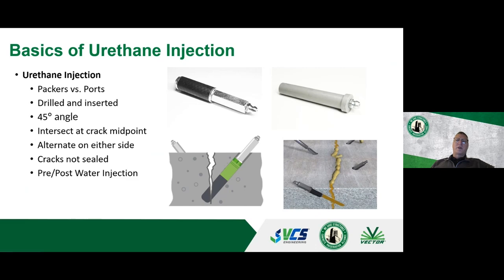As that image in the bottom right-hand side shows, you do not seal the crack because that urethane will spread throughout there. And if you match the proper material with the crack size, it's going to start foaming and expanding and starting to fill all of that. And that's easy enough to scrape off of the surface. But that's your visual cue saying, yes, I have communication. I'm being able to get this to flow and fill this crack and create that waterproof barrier.